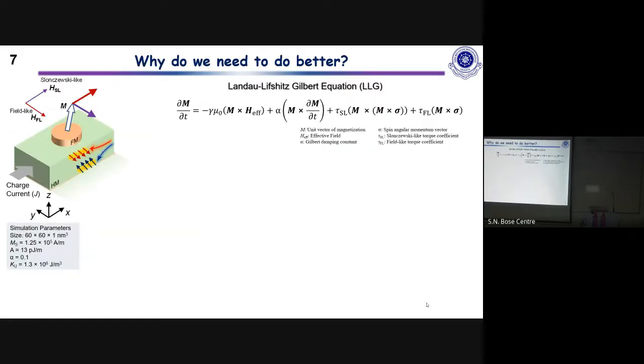To understand why we need the in-plane field, we can look into the Landau-Lifshitz-Gilbert equation of motion, which defines the magnetization dynamics under the application of electrical currents. This is how the equation looks. The first term is the precession under an effective magnetic field, and then we have the damping, and the third and the fourth terms are the ones that are coming from the electrical currents. And we can do this simulation in a